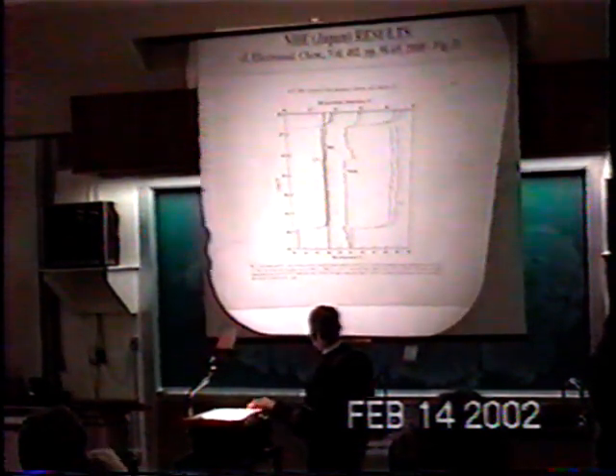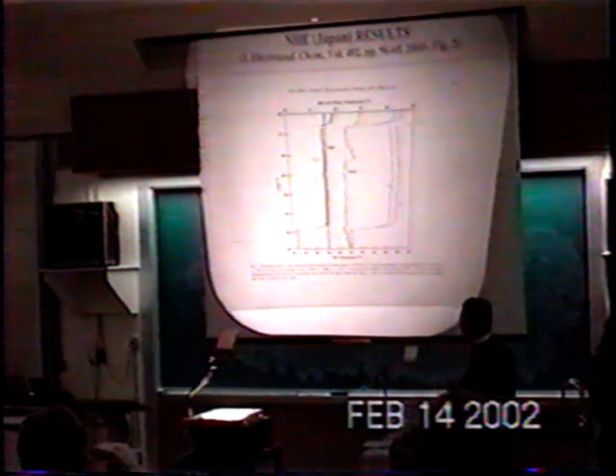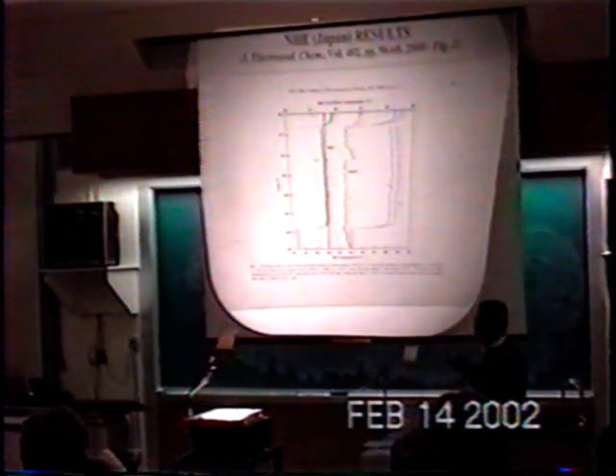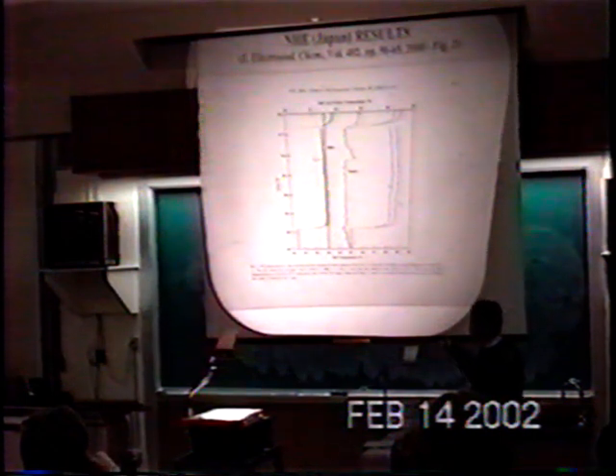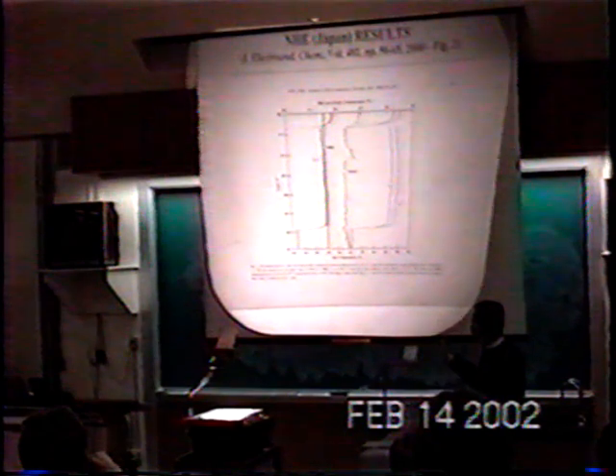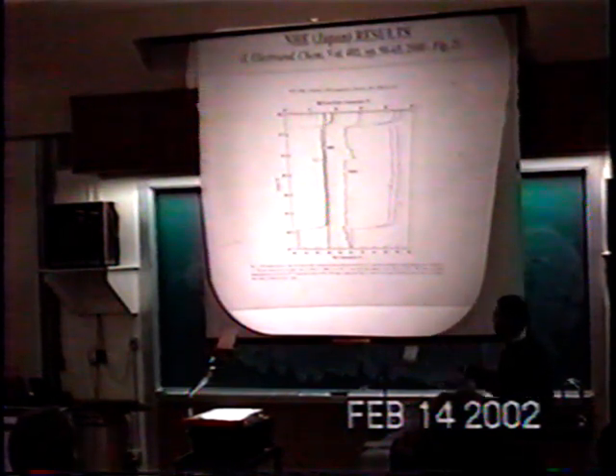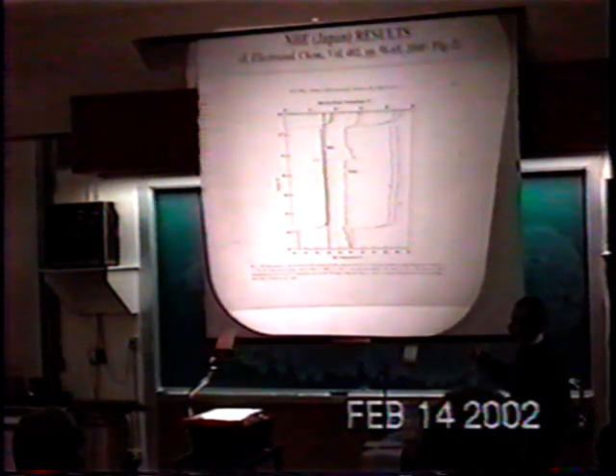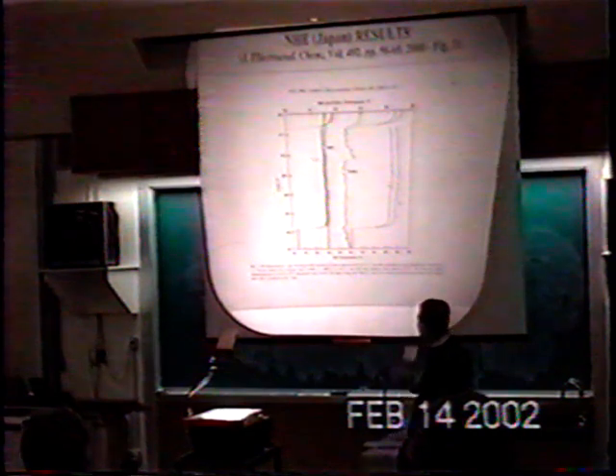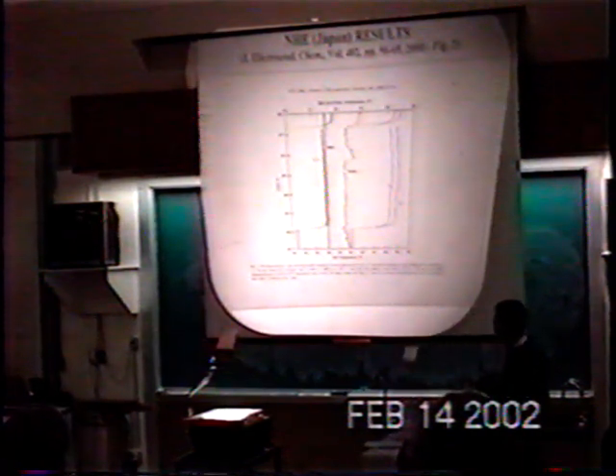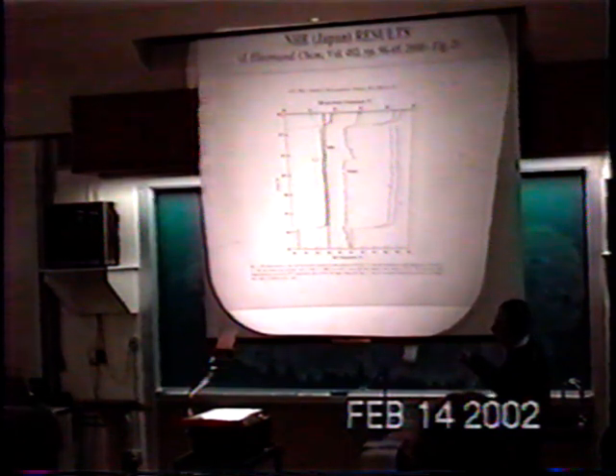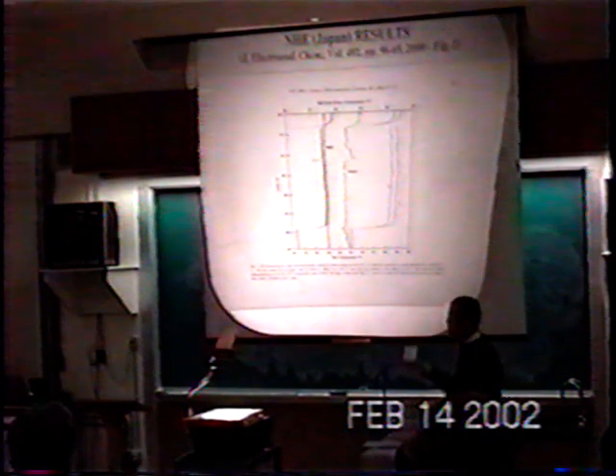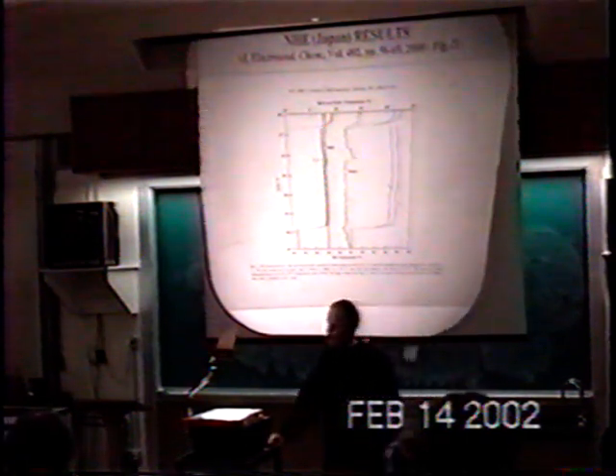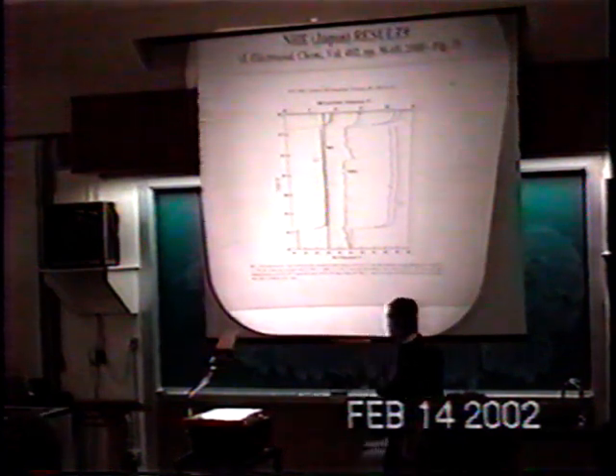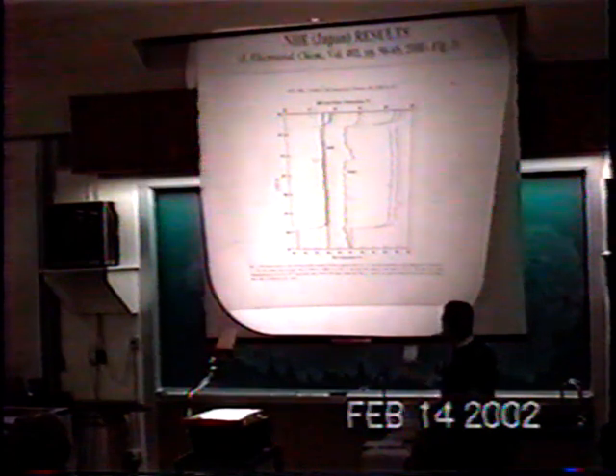Now this is actually from the publication, and there's quite a lot of things on here, so let me explain. We have 6 thermistors. One measures the bath temperature. The bath is controlled. This is the bath temperature scale up here. So the bath is very, very constant, within 100th of a degree actually throughout the experiment. We also measure the room temperature. This is a special room in the laboratory in Japan that is pretty well constant temperature. But the main thing is that we have these 2 thermistors in one cell. This cell never produced excess heat at all throughout this experiment. In a previous experiment using the single electrode at China Lake, it never produced excess heat. That's why I took it to Japan as a control. It never did produce excess heat in Japan or China Lake. This one produced excess heat previously in China Lake. I took it to Japan and produced excess heat again.